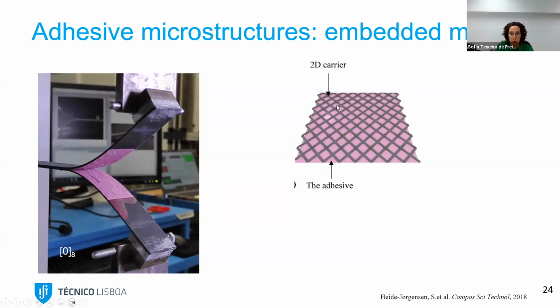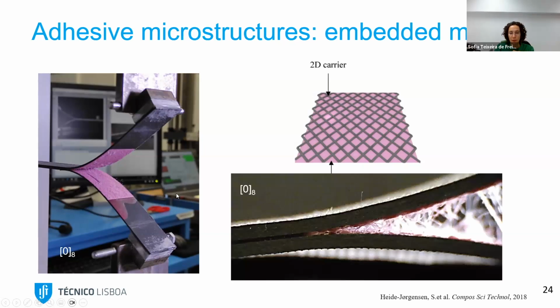As you see here, in this case, it's a 2D carrier. Once we open the fracture, what we see is that this nylon mesh creates bridging mechanisms between the two substrates. So you see here, it looks like a spider web in the region of the fracture surface. So what is the consequence of this in the fracture resistance?